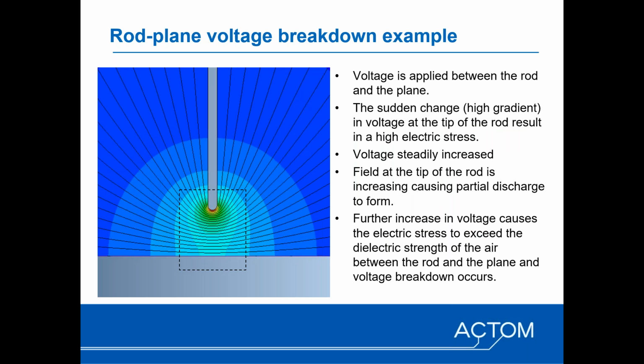Now, the breakdown phenomenon can be explained by an example that we can look at. This is a typical rod-plane scenario where you have an electrode in the form of a rod, and an electrode in the form of a plane. Voltage is applied between the two electrodes, which then gives a voltage distribution in the form of equipotential lines. Where there's a high concentration or a gradient in the voltage, you get electric stresses appearing, which is higher in those areas where the gradient is high.